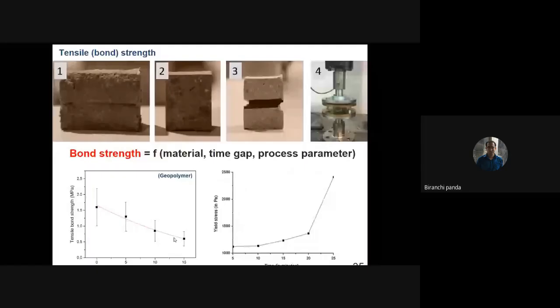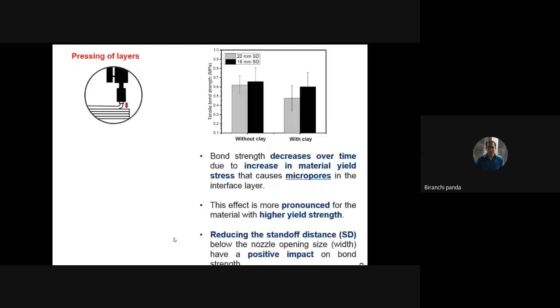How does process parameter affect this bond strength? For that reason, what we have done, during printing, if you slightly press the material, and if the material is slightly softer, these pores can be minimized, because these pores are the main critical points that create very poor bond strength. So during printing, if you can slightly optimize the process parameter, then these pores can be minimized and you can expect a very good tensile strength in such cases.